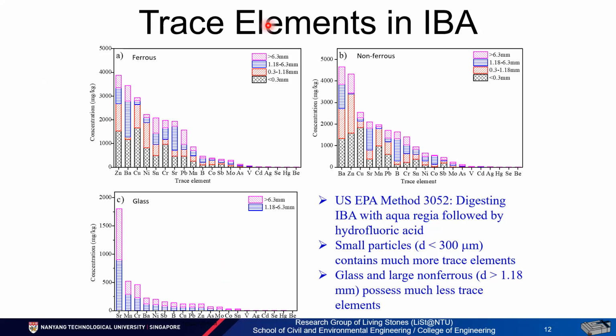About the trace elements, in general we are using this digestion method with hydrofluoric acid. We found that the smaller particles - you will see in the ferrous material - the smaller particles, shown in the black shaded area, often contain much more trace elements.